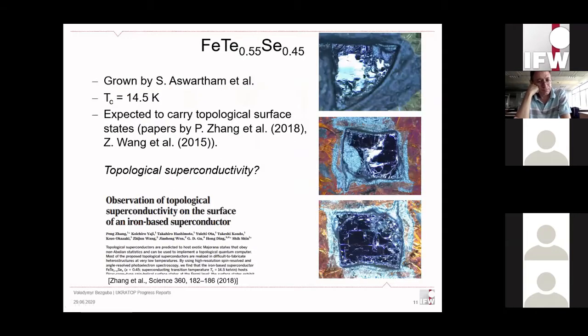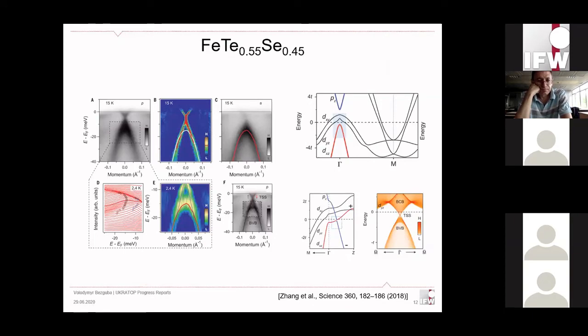The samples which we were measuring were grown by the PSI group. Their critical temperature is around 14.5 Kelvin. And why we got interested in it is because there were several groups reporting this material to carry topological surface states. So it was very interesting to study it by ourselves to get more details.